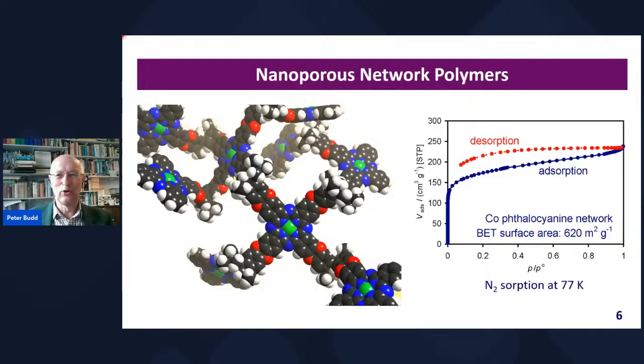It'll meet the adsorption curve at a relative pressure, when we deal with nitrogen at 77 K, of 0.4 or above. But this hysteresis extends to low relative pressures, and that's typical of very many polymeric nanoporous materials, which can perhaps swell a bit and which also have a very complex distribution of micropores.